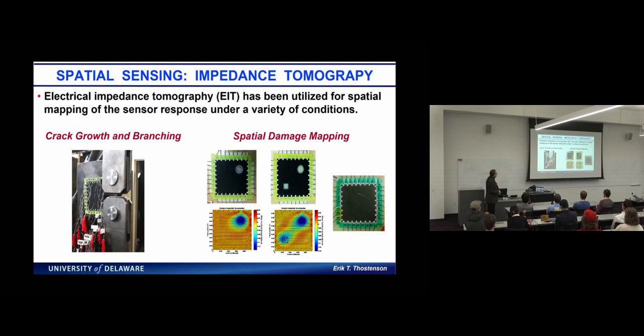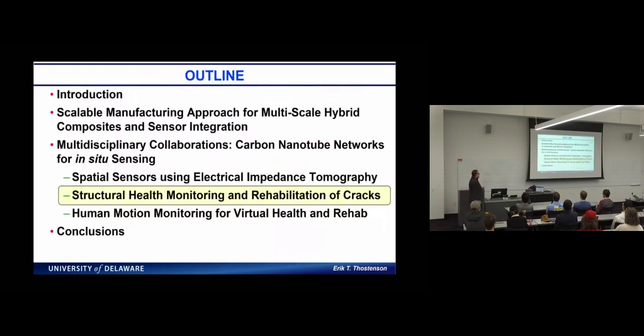But also what we want to do is look at not only the crack growth as a part of a sensor, but where we could add a composite onto the surface. And that composite, when we bond it to the surface, shares the load in the structure, and we can slow the fatigue crack. So this was a multi-year project, as I mentioned. It was funded by the Federal Highway Administration, where we took it just from the idea that we talked to some of our colleagues at the Delaware Department of Transportation, and there was a lot of, especially in the 90s, a lot of research using composite materials to rehabilitate infrastructure.